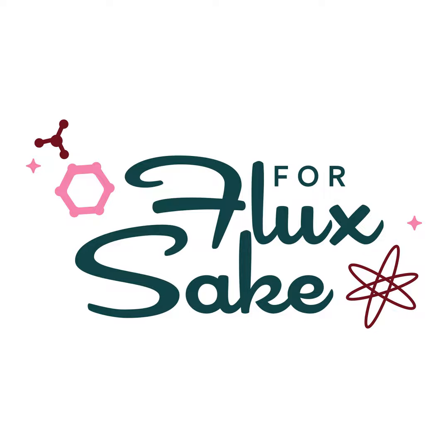But I did just have this student who was testing with ilmenite. And oh boy, let me tell you, she was doing some systematic testing where she was adding it into a glaze as a surface treatment. And she was working with a glaze that was pretty stiff. It was sort of on the upper end of where things will melt, but it was melting okay. But as soon as we started to get that glaze to melt more, it all streaked out. It all just flowed into the glaze and it was no longer a spot. And it just became muddy streaks inside the glaze. And so that's always the contrast. Whereas the manganese, I don't think will do that as much, but in the glaze, I would be pretty skeptical of how effective that's going to be as a whole.